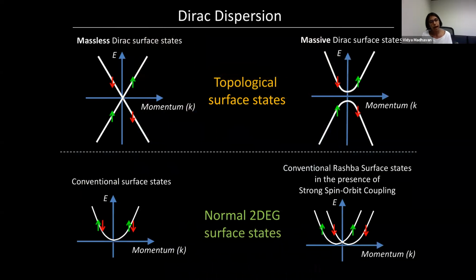Just to give you a sense of how different these states are, if you think of a normal two-dimensional electron gas, for example, take gold or silver, on certain facets of gold and silver, we know that you have this two-dimensional gas of electrons. If you look at their dispersion, these electrons behave like normal electrons in a band, and they have parabolic dispersion. And at any given energy or momentum, you would have two electrons, one spin-up electron and one spin-down electron. If you contrast that with the surface states of a topological insulator, you can see that it's completely different. First, the dispersion is linear, right? So this is Dirac dispersion. Second, at any given energy and momentum, you have only one species of electron. Here I've shown it as spin-up.